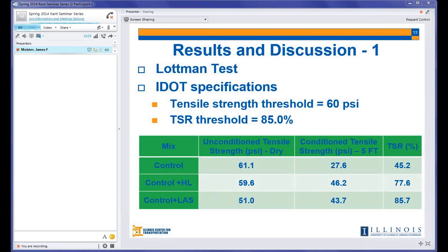But if we go to the conditioned tensile strength, we can see that all of them dropped relative to the unconditioned tensile strength, which makes sense. But the important numbers are at the end. The huge drop was seen for the control mix. Only 45% of the tensile strength was sustained after 5 freezing-thawing cycles. So a huge drop in the control mix after conditioning. While for the lime and liquid antistrip, the performance was better. Only 23% and 14.3% were lost after conditioning, with 77% and 85.7% sustained.